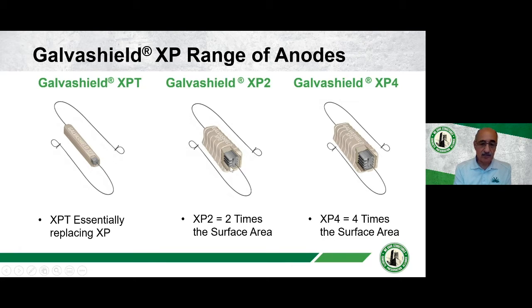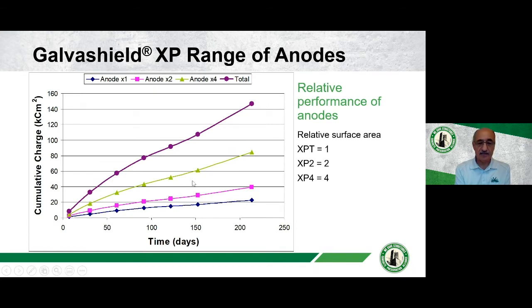We have a 2 times larger surface area anode, which we call XP2, and a 4 times larger anode, which is called XP4. So the current output increases as we increase the surface area, and we were able to see that in some of our early studies when we were first making the anode. And you can see the current from the lowest surface area, it then doubles and then it's 4 times higher.